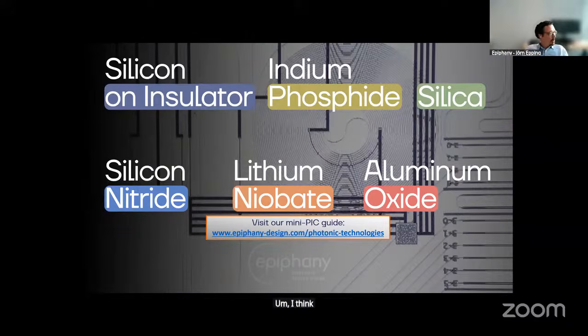I think from our point of view, silicon on insulator still has the highest traction at the moment. It was not covered in here, but it's the most mature, it's closest to semicon. And so I think what Hamid said had very good points, right? Why not use the maturity of silicon on insulator and add your secret sauce of lithium niobate on it? I think that's a generally valid approach. Same goes for indium phosphide. Indium phosphide can also be very well co-integrated with other technologies, for example, like XFAB is doing.